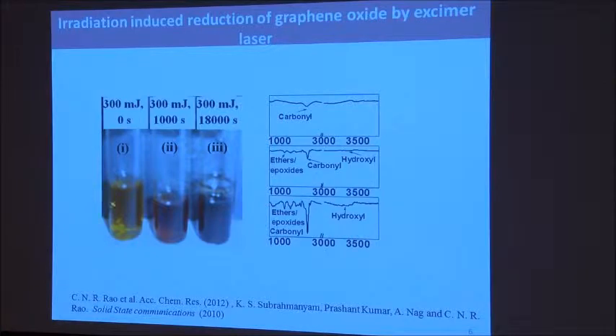One of the nice ways, even physicists can use, is making single layer graphene oxide in solution, a yellow solution. Just put it in sunlight, or if not sunlight, use UV light or laser irradiation. Slowly that yellow solution becomes black, and you have nice graphene dispersed in a solvent. You can see by looking at the infrared spectrum how all the oxygen functionalities in graphene oxide disappear as you irradiate with laser radiation or ultraviolet light.